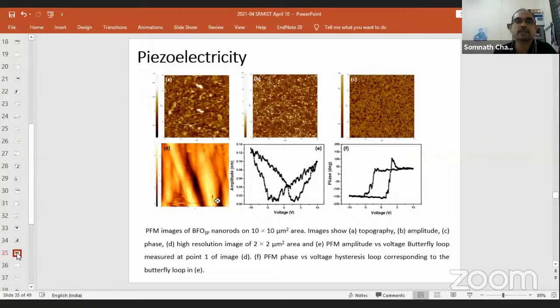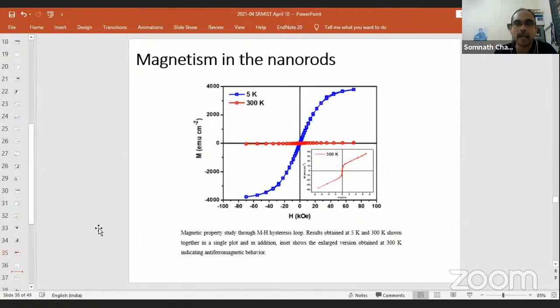So we checked for piezoelectricity. In fact, as in the lower one, what I call the beautiful butterfly, again, which actually confirmed the bismuth ferrite was there. Of course, XRD also confirmed, but XRD shows mixed phase. This actually 100% confirmed that we have piezoelectricity or ferroelectricity in the material, so it is a multiferroic compound. Then again, we ran magnetism. Of course, the magnetic values, the susceptibility and magnetization values, are extremely small because of the presence of the mixed phase, as also because the nanorod is extremely short.